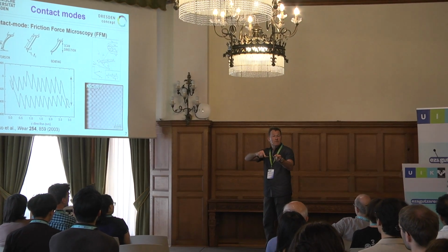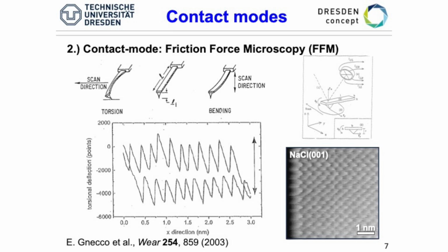start scanning laterally. What happens is, naturally, that when you scan, your tip sticks, and you go, that's my hand, I want to scan here, on the backside. But the tip stays until it's basically there, and then bang, it snaps over to the next atom. So we get exactly a snap-in on the atomic scale. And this is exactly measured here on sodium chloride.